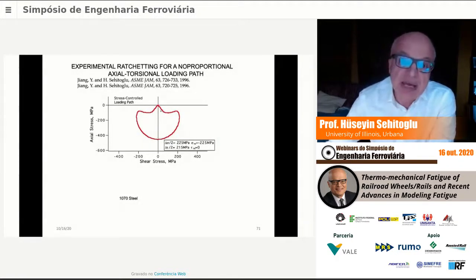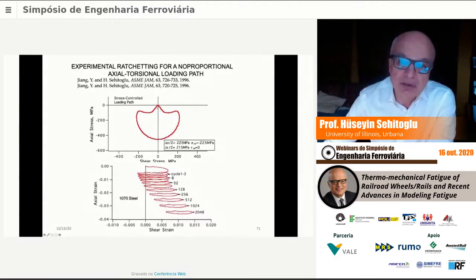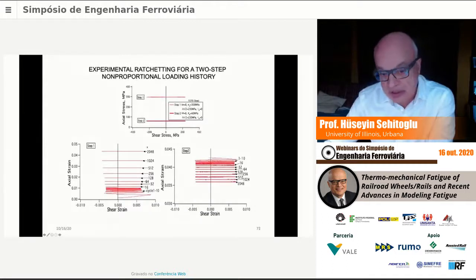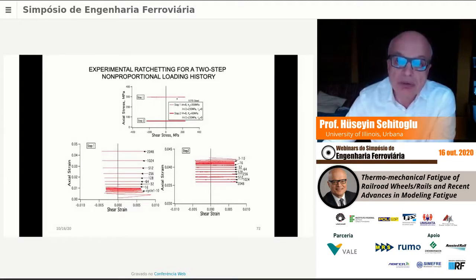Now the constitutive model that we've developed is listed in these two papers. This is Journal of Applied Mechanics, ASME, 1996. Again, this is my history. So this is shear in the other direction, back to zero. So this is one path, so to speak. And this is a non-proportional loading because the axial stress and the shear stress are changing in a non-proportional way. That's the ratcheting, the shear strain variation with cycles. That's the experimental result. And one can do these experiments, keep the axial stress constant, and then reverse the shear stress.